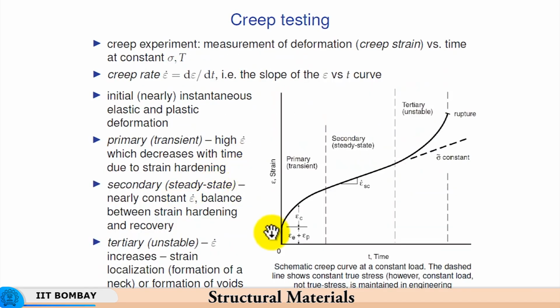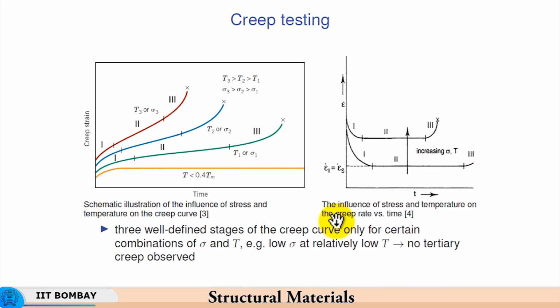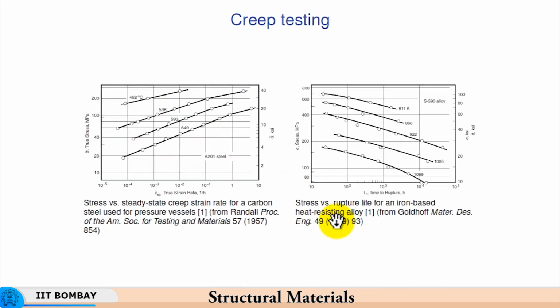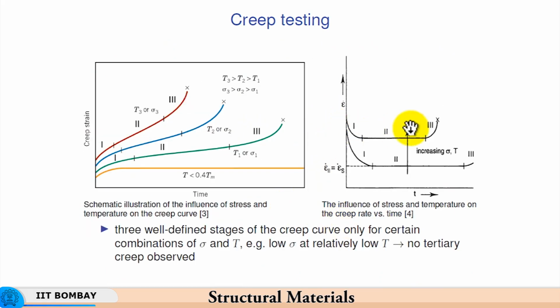So, generally we have three stages of creep. One is the steady state creep, which is of interest to us. The primary creep is the transient creep, which lasts for a very short period of time. But this steady state is the most important zone. So, we need to widen this zone to the extent possible and not get into the tertiary creep region until the material ruptures. We have seen the corresponding creep strains and the effect of stress and temperature.